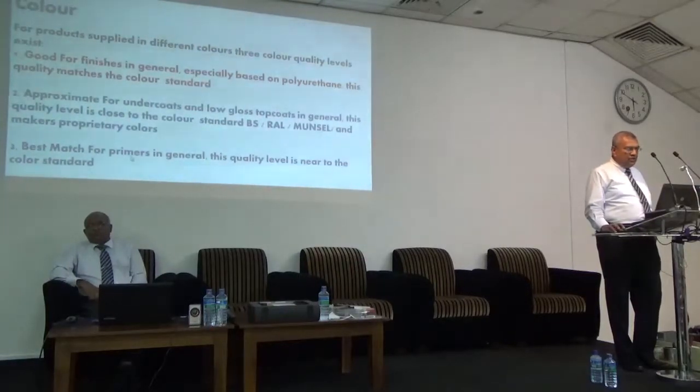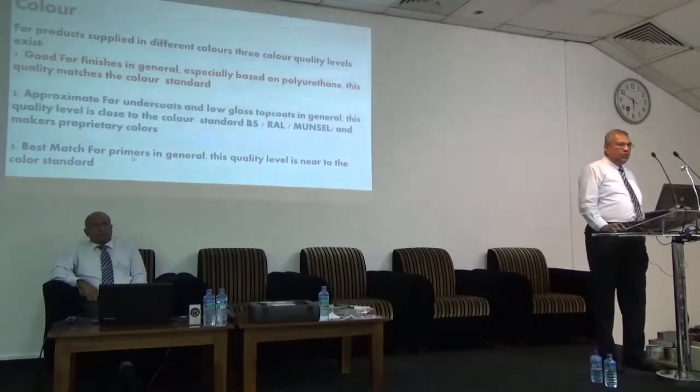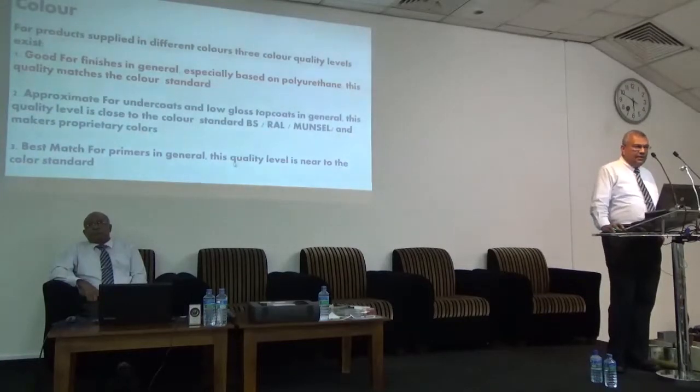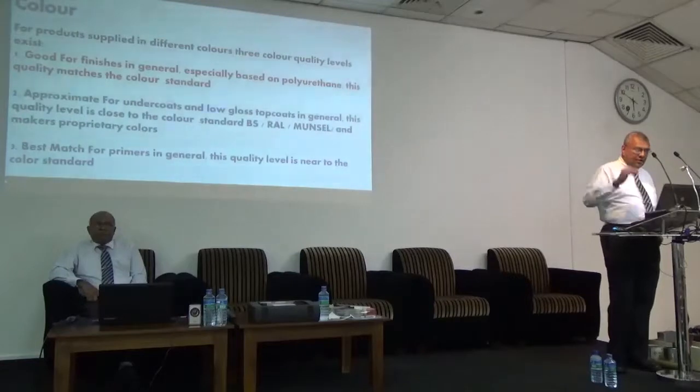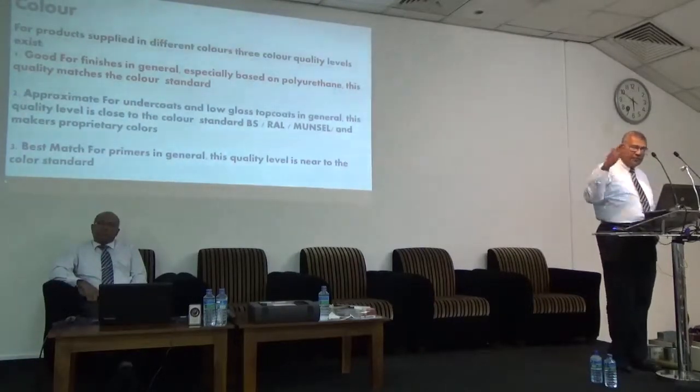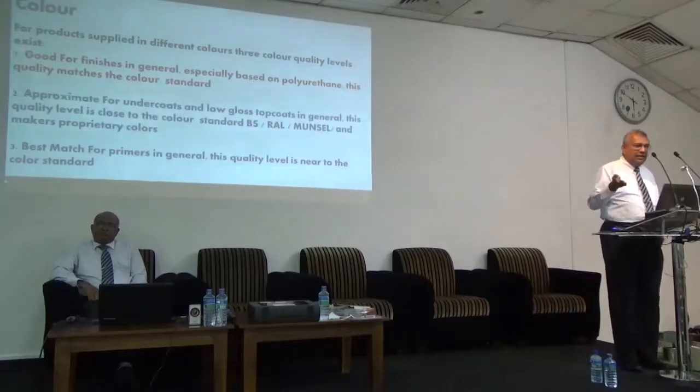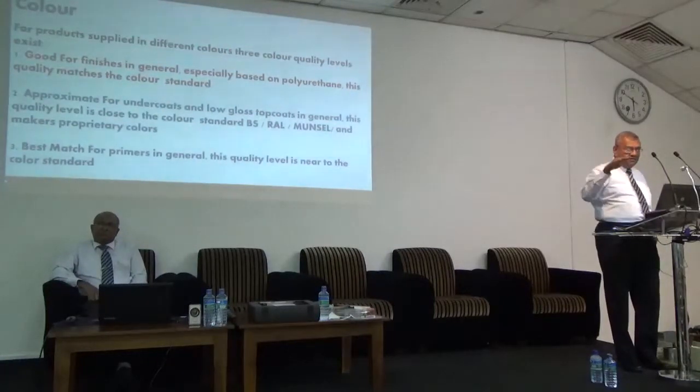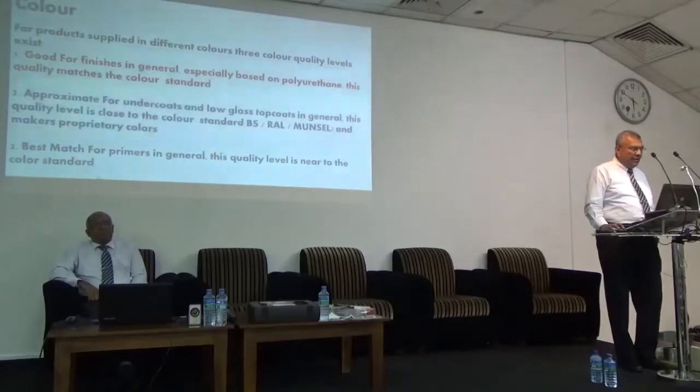The primer has to be matched with the color also sometimes. If you have a dark red primer, you have to put a dark color on top. If you have a light color underneath as primer, then you can cover it well with a white color shade. So you have to select the color shade according to the primer color. Because if you use a dark one and try to put white paint, you need 3 coats, because you can't hide it. So you need to plan it. What we do is, you have a dark red primer, and for the intermediate you put a grey color, and the finish is white. Then the paint hiding factor is very good.